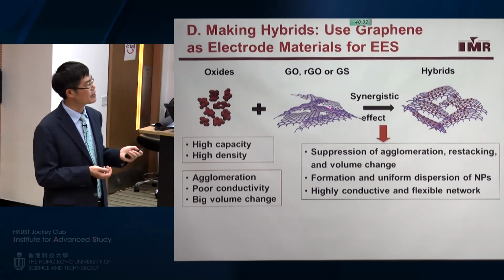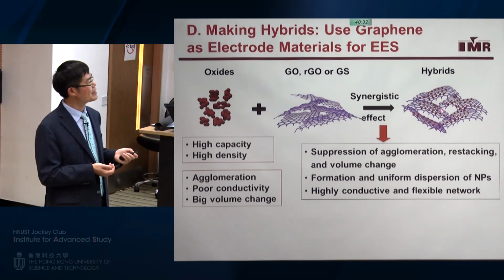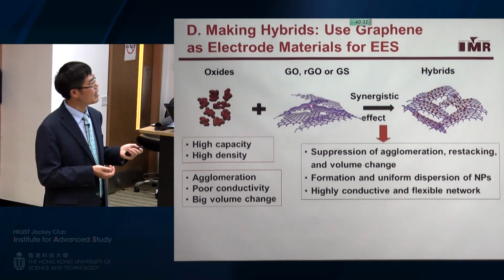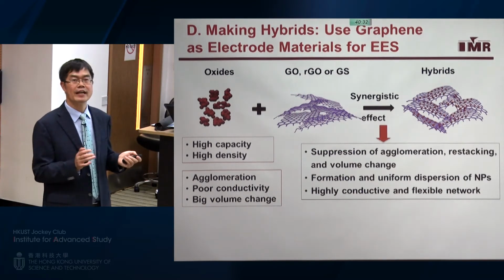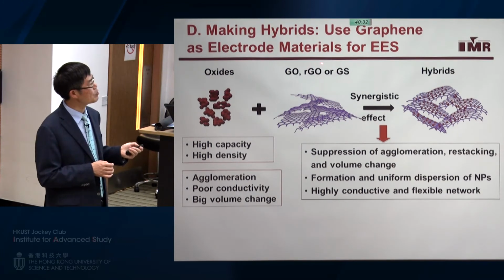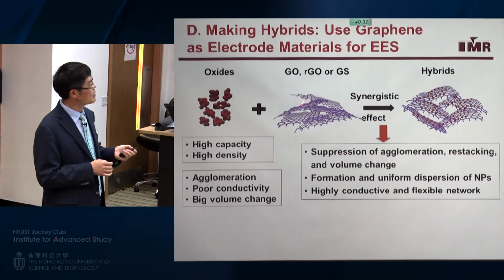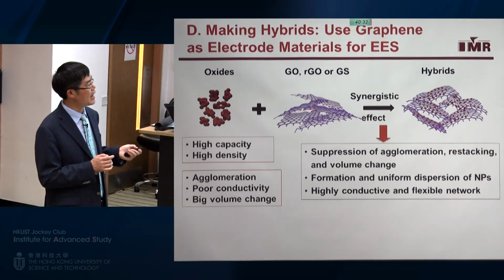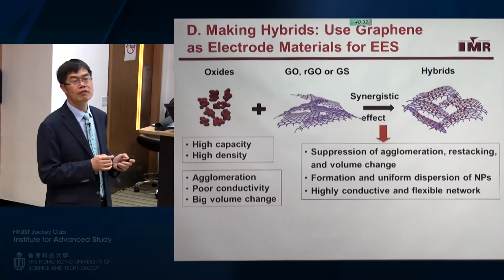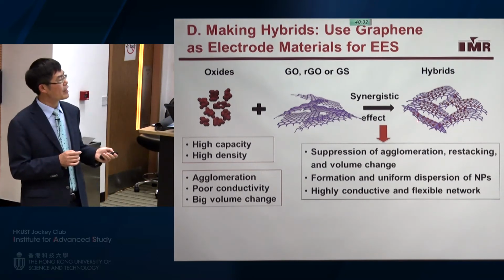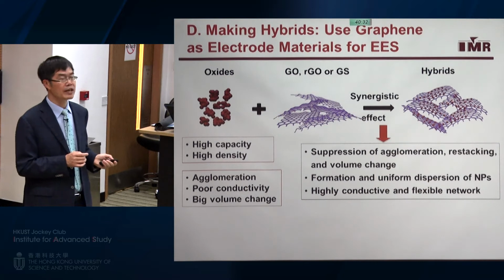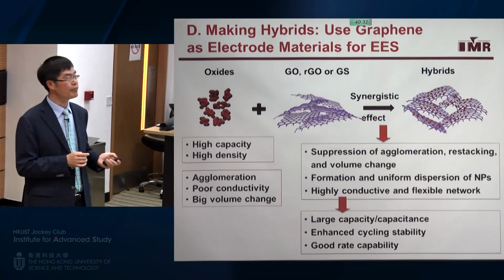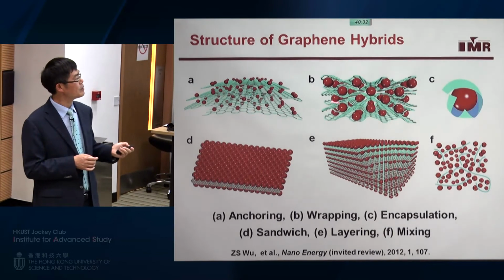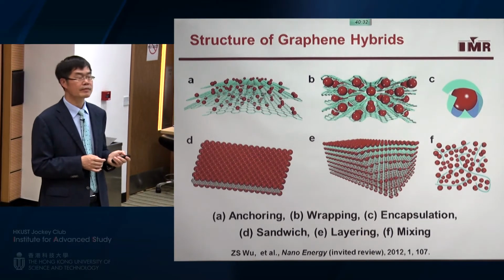We also found that because there are many functional groups and defects on the graphene oxide or reduced graphene oxide, the oxide is ready to nucleate at those sites to form uniformly dispersed nanoparticles of oxide. And also, graphene can form a highly conductive and flexible network. In this way, we can improve the performance. And also, we can have different kinds of structures.